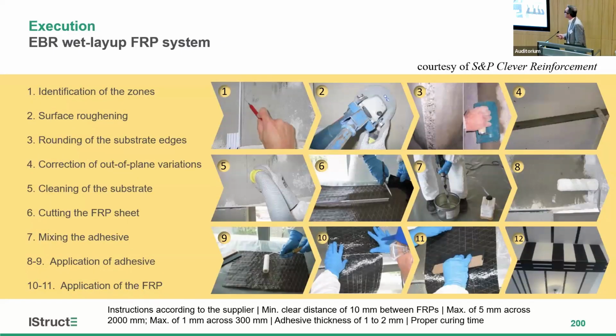In the case of external bond reinforcement with wet layup systems, the procedure is relatively similar, but in the case, for instance, of applying shear strengthening, we have to round the edges. Again, if you go to the codes, you'll see the minimum radius that is recommended for this. Otherwise, we'll have failure at these corners.